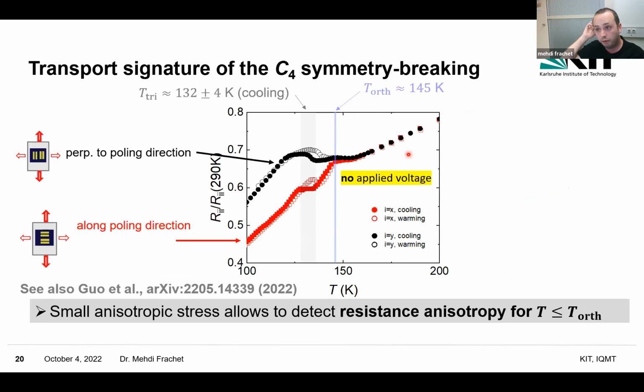Actually that's quite fortunate because it allowed us to see a transport signature of the rotational symmetry breaking. What you can see on this graph is resistance as a function of temperature of a BaNi2As2 sample, which was glued to the piezo. We measured electrical resistance in the two directions. In black, you can see the resistance measured perpendicular to the poling direction, and in red the resistance measured along the poling direction. The filled symbols are taken upon cooling, and the empty ones upon warming.